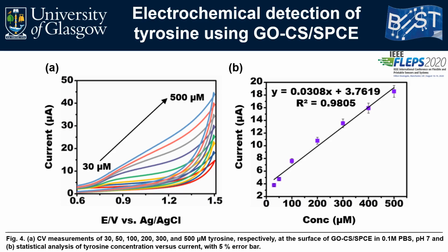The oxidation peak current also continued to increase with an increase in tyrosine concentration. As can be seen in Figure 4b, the measured oxidation current had a linear relationship with the concentration of tyrosine, demonstrating a correlation coefficient of 0.9805. The graphene oxide Chitosan screen-printed carbon electrode also exhibited a high sensitivity of 0.03 microamps per micromolar.